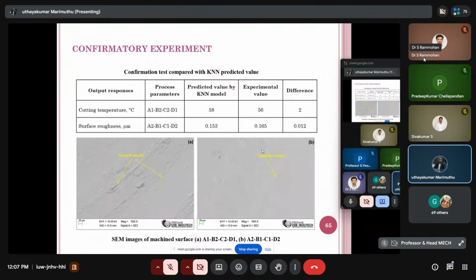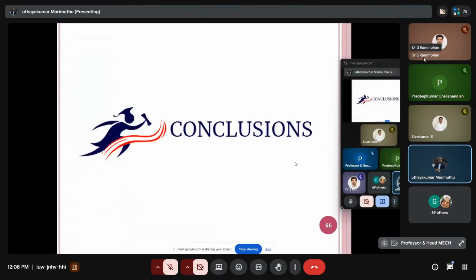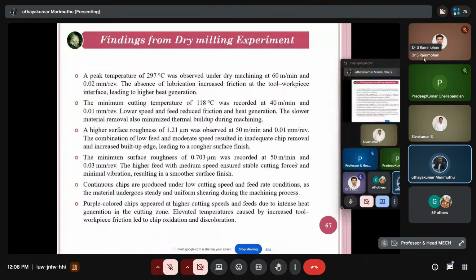This one we took from the PhD deck. So how the scratch model appears, and how the smooth surface is exposed. So those things are done. Now coming to the conclusions: a peak temperature of 297 degrees centigrade was observed under dry machining at 60 meter per minute and 0.02 mm per revolution. In that case, there is an absence of lubrication.